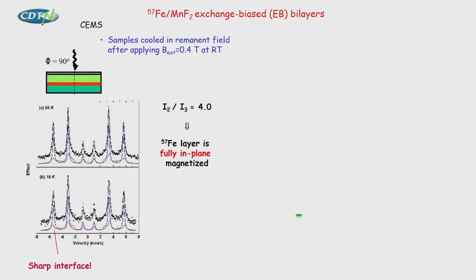Okay? And as you can see here, we have two things in this spectrum. First, we see that this alpha iron spectrum has a contribution that is the interface. It's very small, which means we have a very sharp interface in the system. And from the intensity of the lines, we see that we have a fully in-plane magnetized sample.